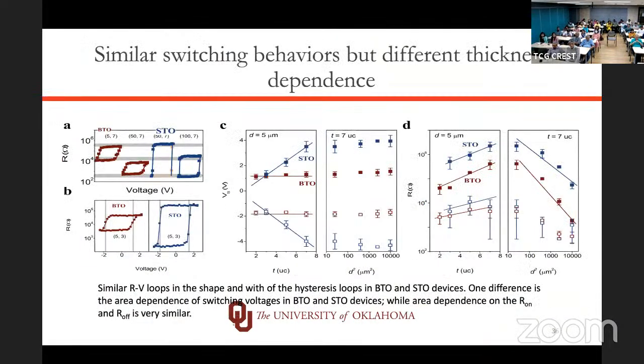Also, I'm going to show you another example where barium titanate, this is strontium titanate, and barium titanate, the switching here is completely from tunneling effect. In strontium titanate, this switching is from what's called oxygen vacancy formation. So oxygen vacancies form, and these oxygen vacancies are charged, so they can effectively short circuit an electrode. So as I'm changing the voltage, oxygen vacancies are forming and they reach a percolation and suddenly the device switches. So this is purely from oxygen vacancy effect. And you can see the voltage dependence and the thickness dependence very clearly.